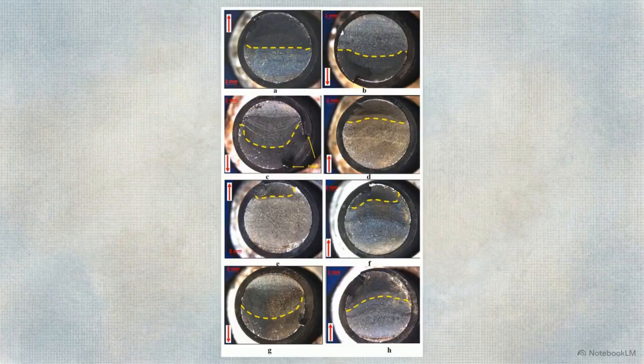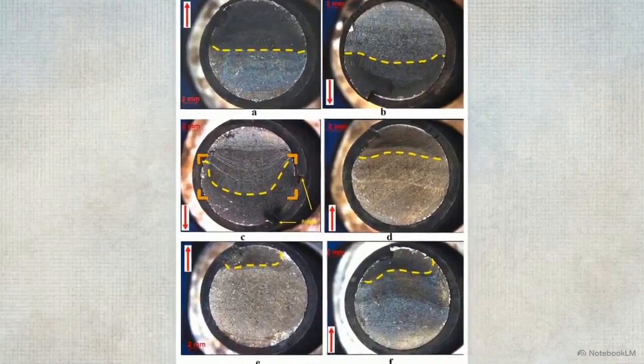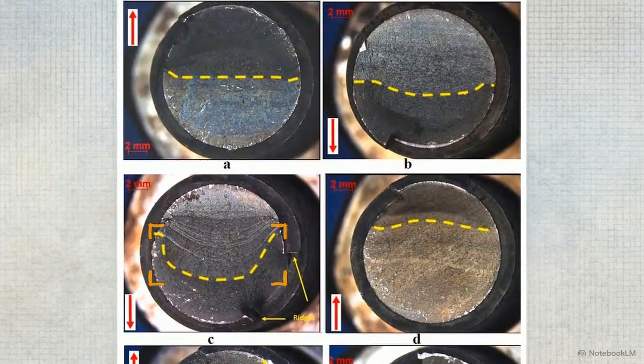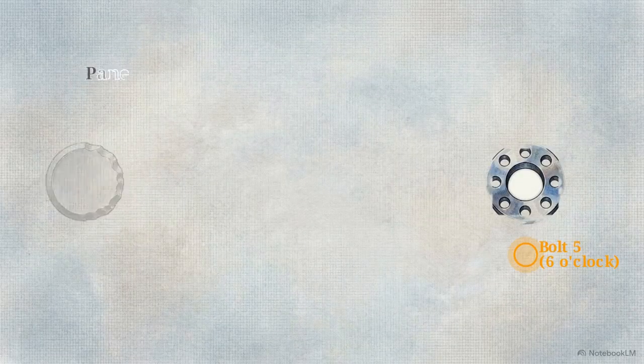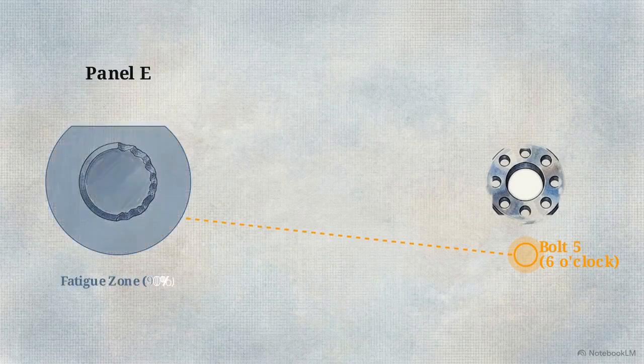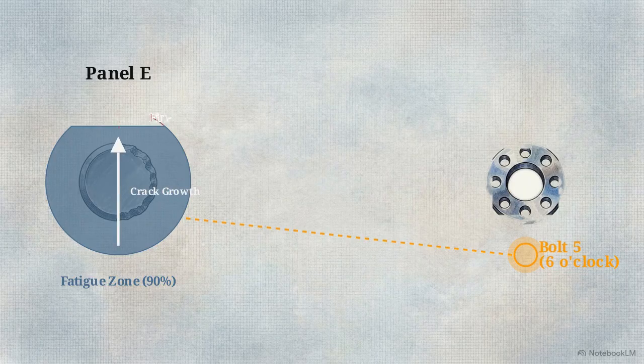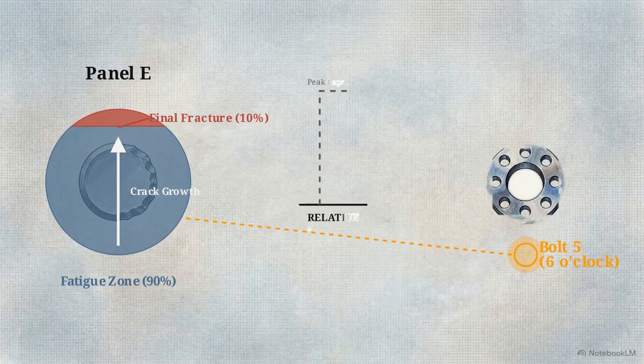Here we have the array of all 8 fractured bolt faces, laid out sequentially from position 1 through 8. The dashed yellow lines separate the slow fatigue growth from the fast final fracture. Focusing on panel E, which corresponds to bolt 5 at the dead center 6 o'clock position, the smooth fatigue area is massive. The crack had to travel almost completely through the bolt before the remaining steel finally gave way, proving this position experienced the lowest relative stress.